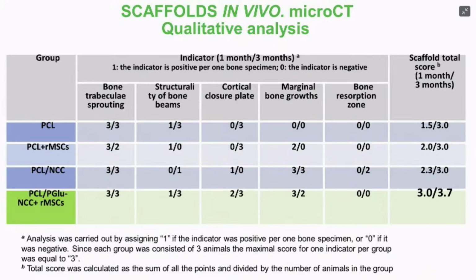This table. According to our analysis of microcomputed tomography images, we can conclude that after 1 and 3 months of surgery, the larger volume of mineralized bone tissue was observed in the group with polyglutamic acid modified nanocrystalline cellulose and seeded with MSCs. This one. The growth of new bone trabeculi into the scaffold, bridging of the defect area, as well as the formation of bone callus in case of this group, marked green. So all these factors confirmed that this material was biocompatible and had at least some osteogenic nature.